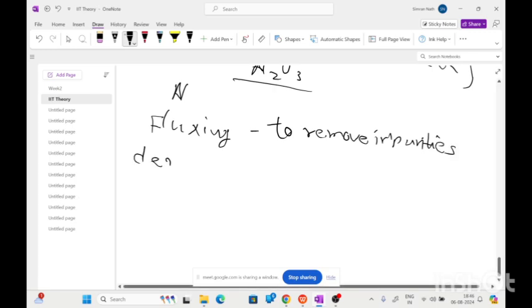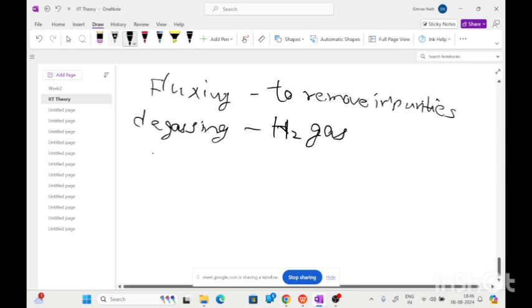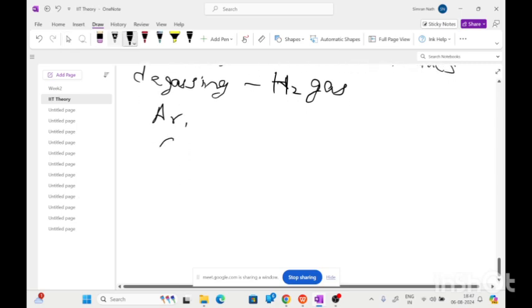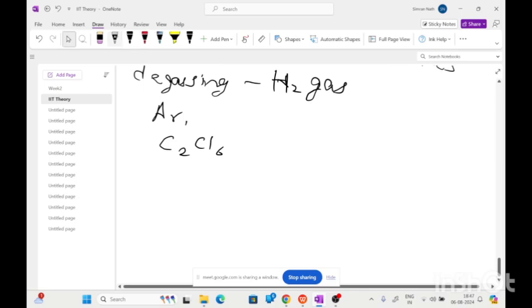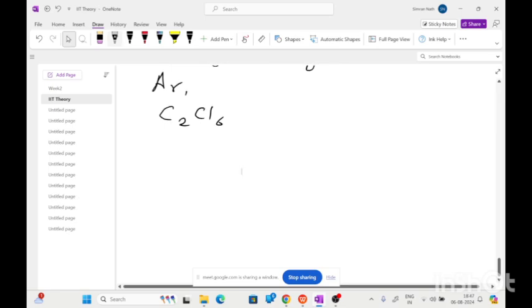Second is degassing. Degassing is used to remove the hydrogen gas from the aluminium melt. Degassing can be done by inert gas purging, like argon, and by adding degassing tablets. Degassing tablets have the composition C2Cl6. So these tablets are used for degassing in the aluminium.